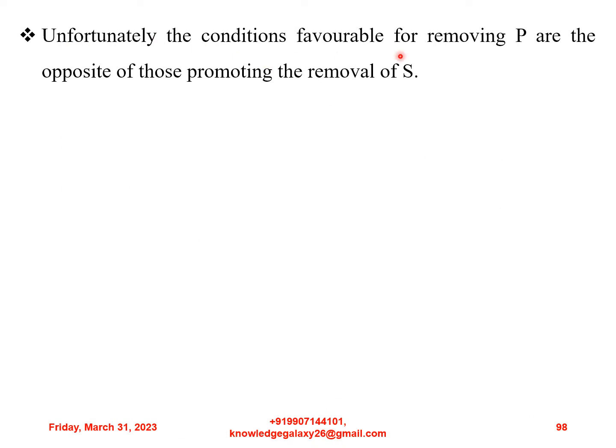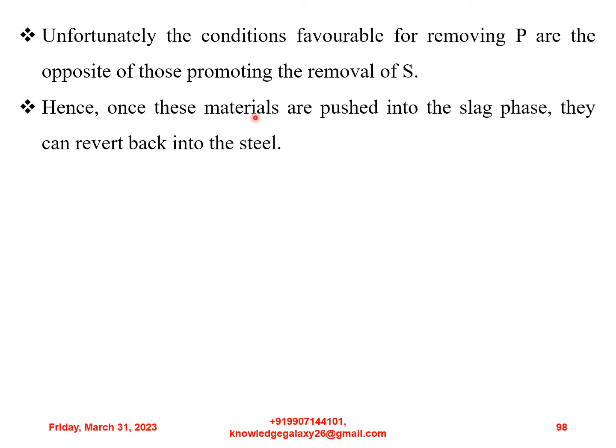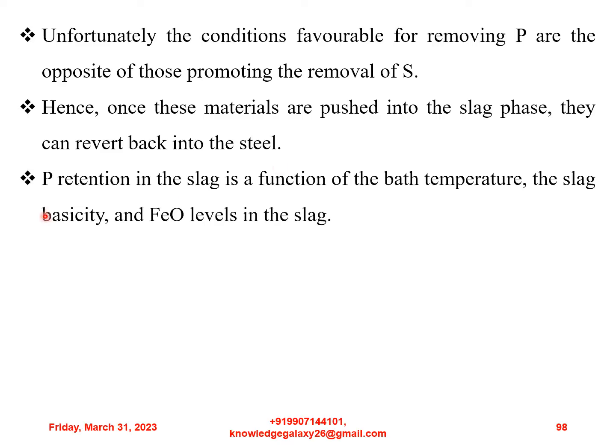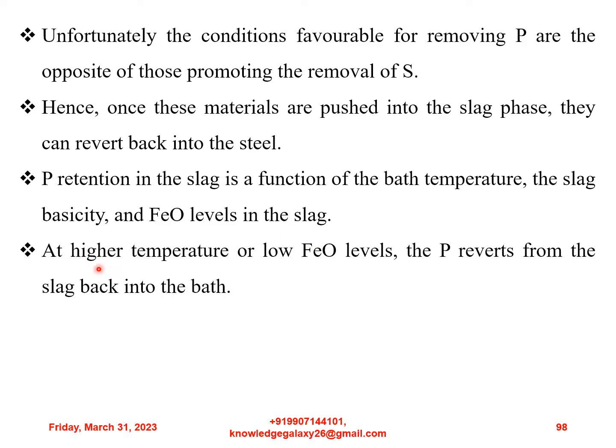Unfortunately, the conditions favorable for removing phosphorus are the opposite of those promoting the removal of sulfur. Hence, once these materials are pushed into the slag phase, they can revert back into the steel. Phosphorus retention in the slag is a function of the bath temperature, the slag basicity, and the FeO levels in the slag. At higher temperatures or low FeO levels, the phosphorus reverts from the slag back into the bath.